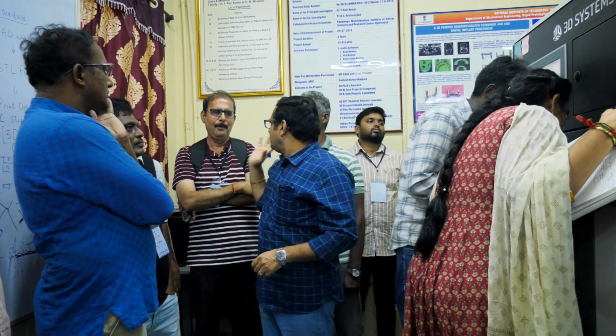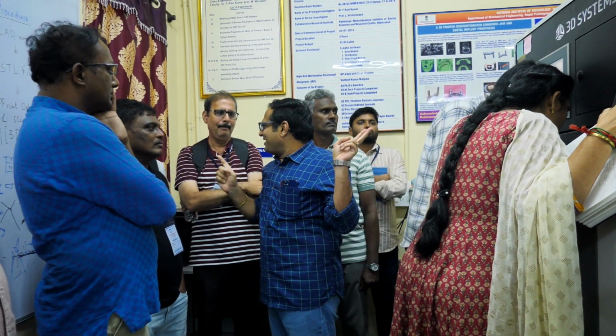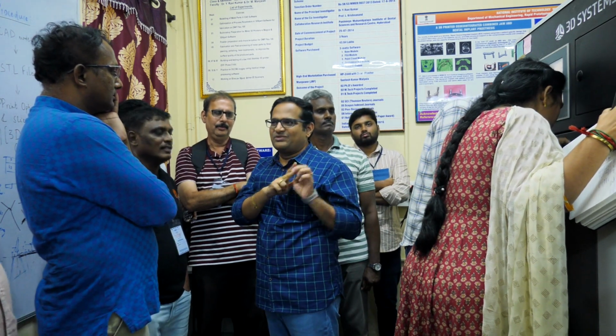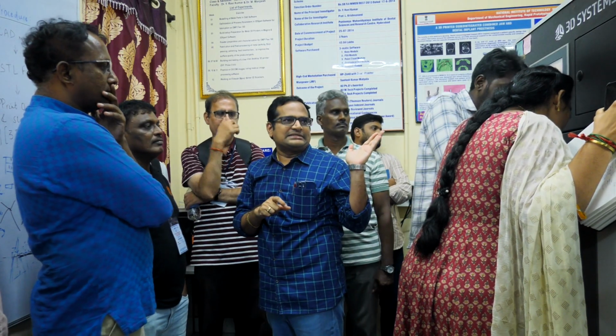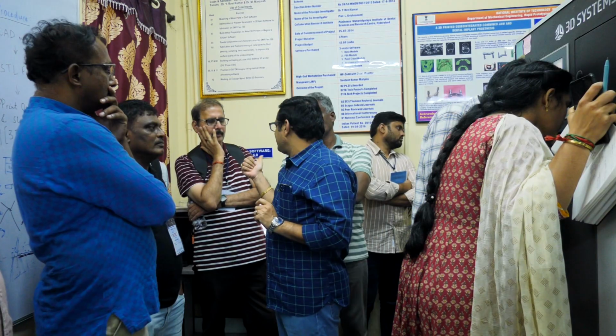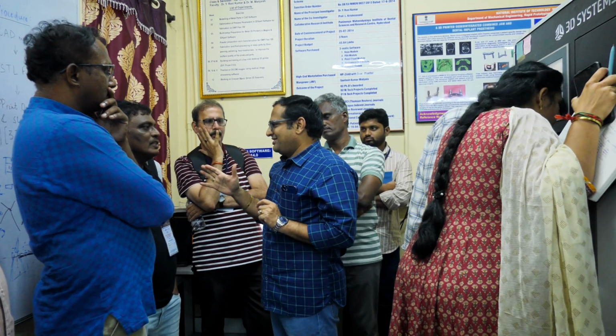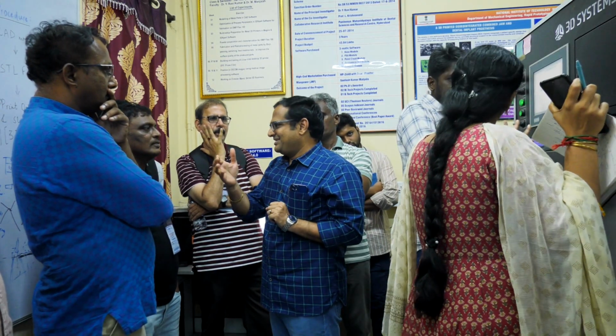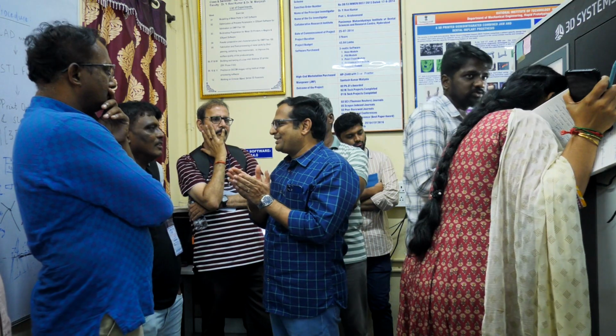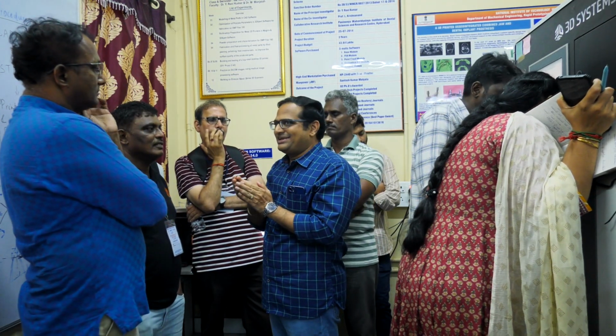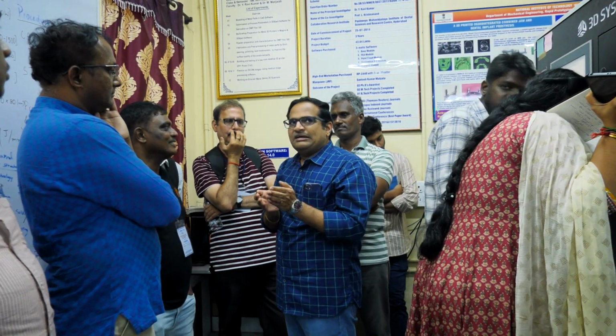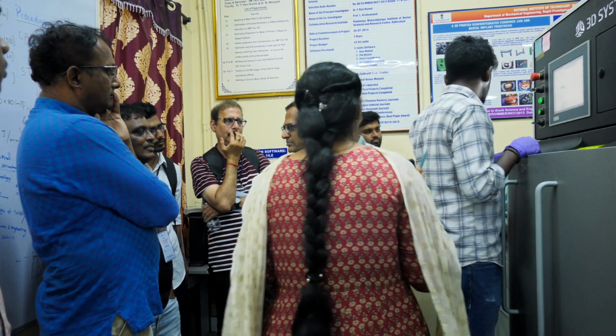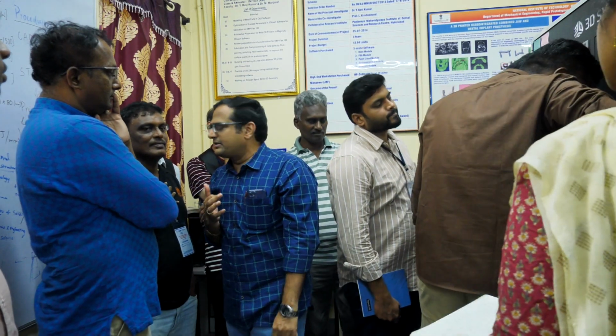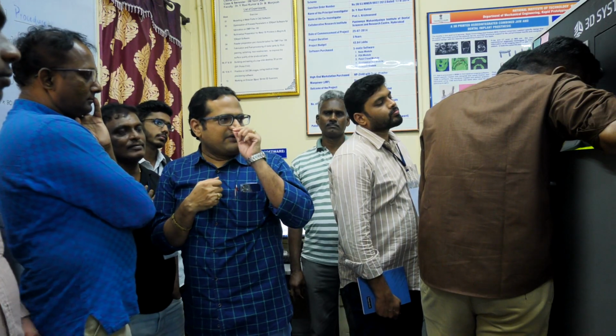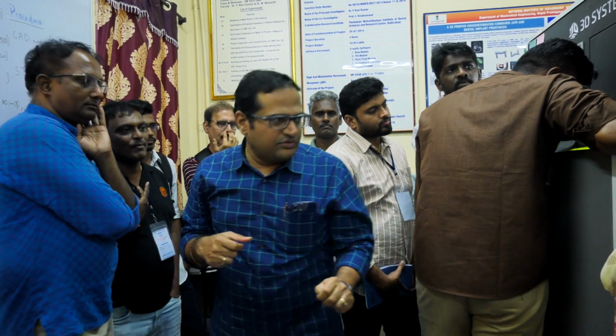Basically, we have to supply argon gas. Inert gas is argon, and we have two options. Argon goes with titanium, and nitrogen goes with the steel, for reactive and non-reactive materials, because argon is a bit more expensive than nitrogen. Nitrogen will go with steel, cobalt chrome, and aluminum. Argon is for higher-end applications, like titanium. And we have a compressor also for pumping.